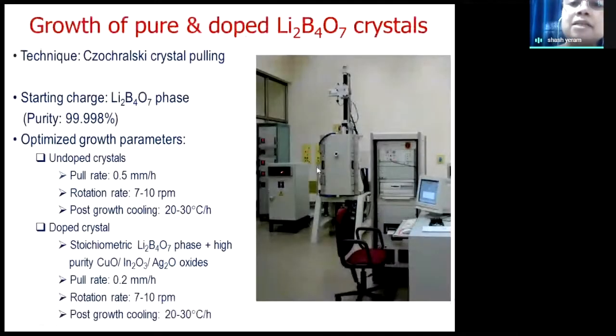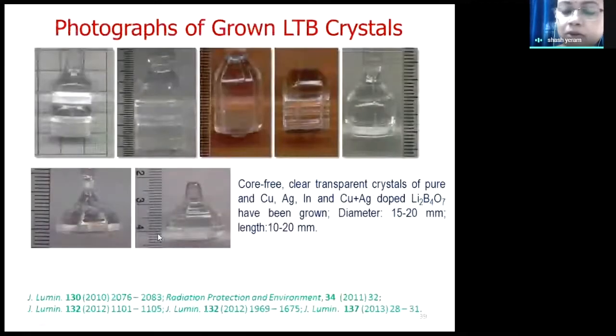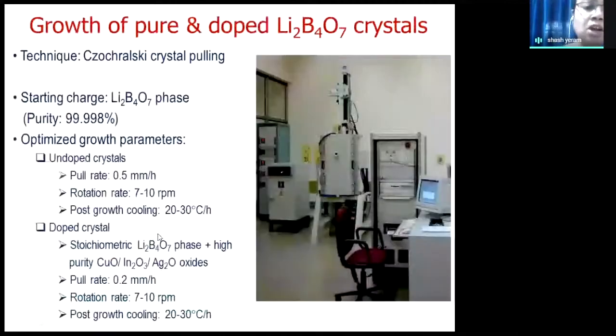So this material is one of the very good dosimetric materials which our group has worked on. This is lithium tetraborate. Lithium borate crystals are also grown by the Czochralski technique, but its melting point is quite low, around 900 degrees centigrade. So not very difficult to grow, but there are difficulties in this growth because it grows at a very small speed, and we have to do a lot of material engineering to get good dosimetric output.